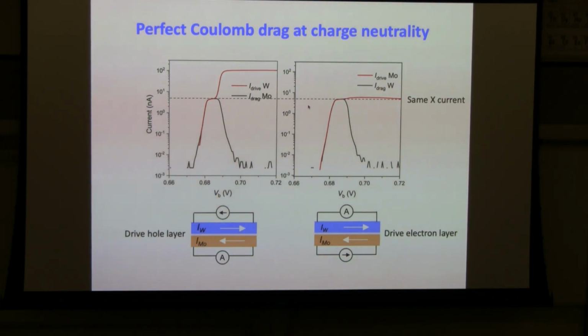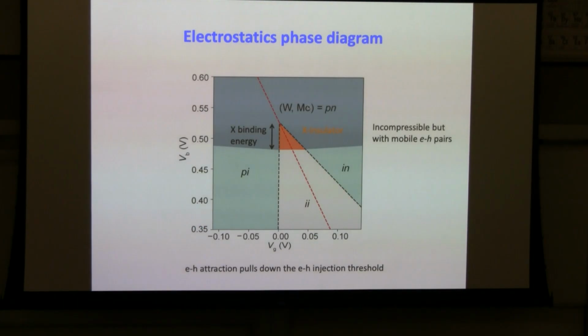Even if you switch which layer to drive or drag, you still get the same exciton current, because in this region, the exciton current is only limited by the contact resistance of the entire double layer. So you should get the same exciton current in both situations. Okay, so I hope this is convincing enough. To briefly cap, this is the phase diagram with VB and VG. Because of electron-hole interaction, that will pull down the electron-hole injection threshold, which is this line here, by an amount equal to the exciton binding energy. And within this triangular region, we have a charge insulating state, but there is a spontaneous fluid of excitons populated in the system.